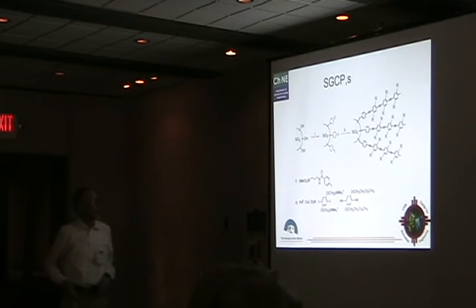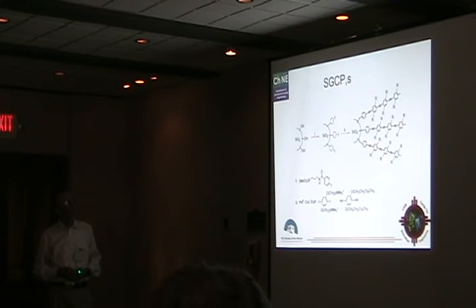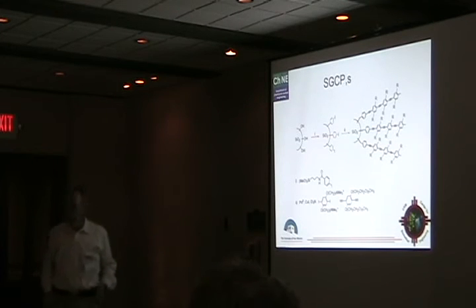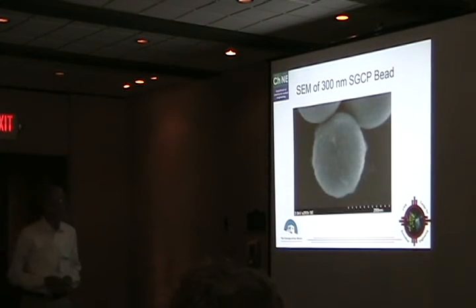I'm coming back, though, now at the end to the surface-grafted conjugated polymers, and where we find they may be very useful is when we make the cationic counterparts of the conjugated polymers I showed you earlier, where we have the pendant quaternary ammonium groups, and so we have the cationic polymer grown off. And we find, once again, that if we look at these, say by electron microscopy, you see that the surface is very ragged. It looks like what we can expect from a polymer brush.